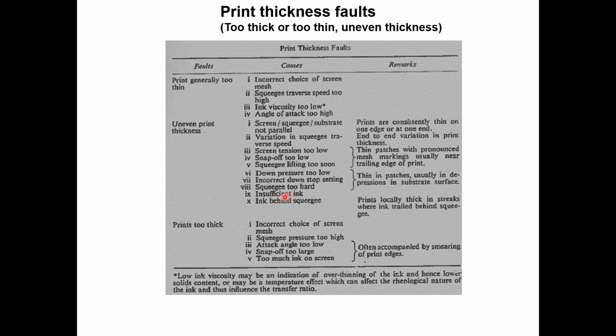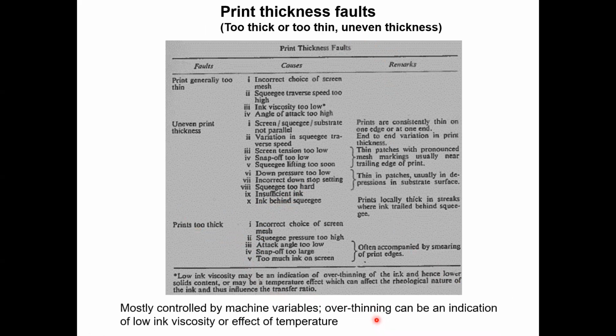Now, you also can get all kinds of faults in the printed film, too thick or too thin or uneven thickness. And again, it will depend both on machine variables. Over-thinning can be an indication of low viscosity or the effect of temperature. So there are both machine variables as well as ink properties that will create different types of thickness faults in the printed film.